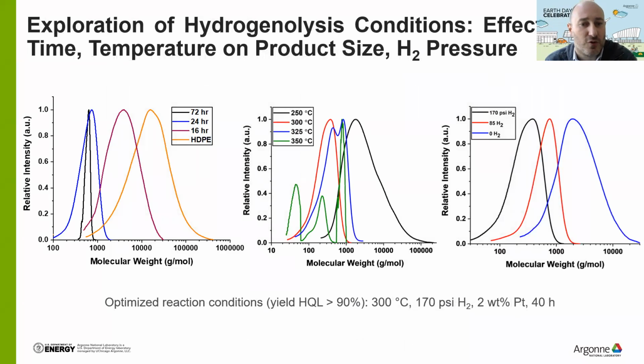We also try to optimize the reaction condition. We look at reaction time, temperature, hydrogen pressure, and platinum loading. For example, very interesting on the temperature, when we pass the 300 degrees mark, we started to observe thermal decomposition of the plastics, called pyrolysis.